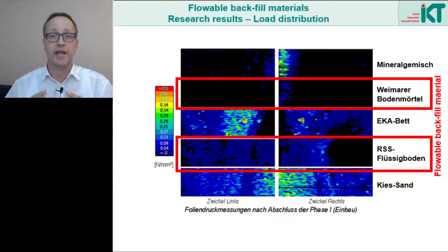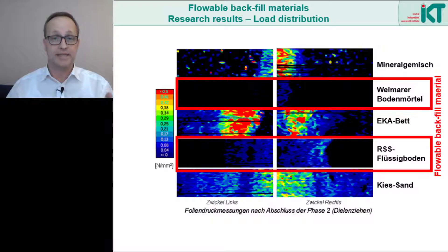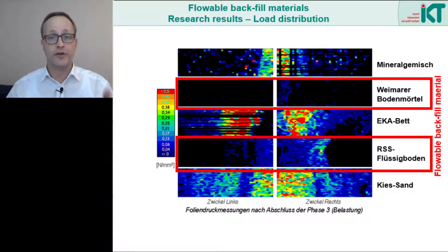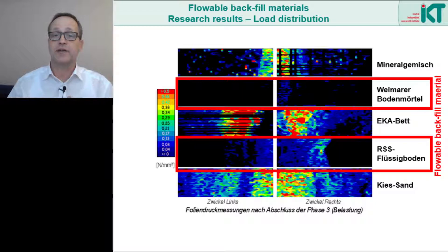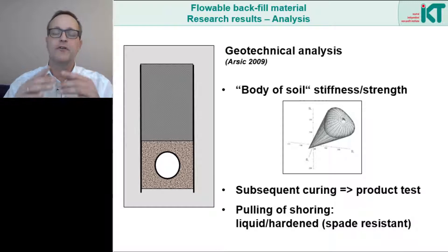In the second and fourth rows we see the results of the support reaction for the flowable materials. Already after curing and first loading it became clear that the initially liquid materials produce a very even, hardly measurable support stress. This impression even intensifies after the pulling of the shoring and after further simulation of traffic loads. These experiments have contributed much to the understanding of the system of flowable backfill and pipe. Further tests to compare even more flowable backfill materials were carried out later, but those results will be reported in another video.